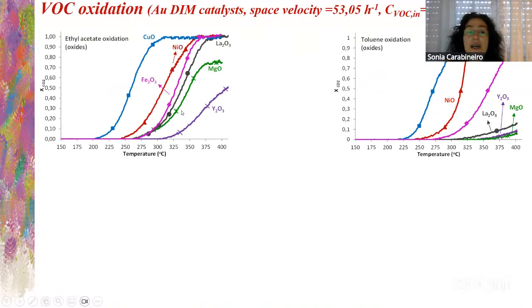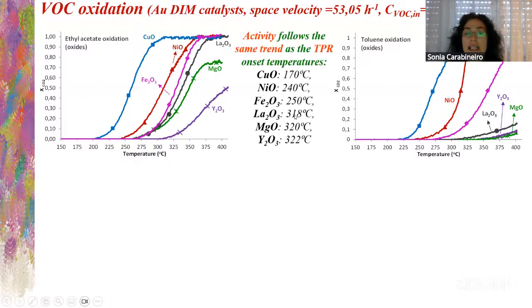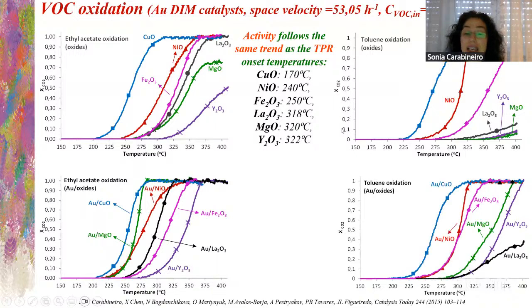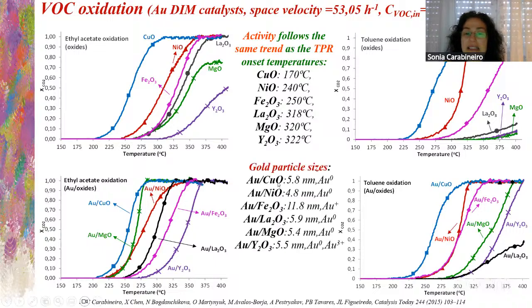Here it's several oxides, okay, several oxides for ethyl acetate and for toluene oxidation, for the oxidation of two different VOCs. And you see that the activity follows the trend of the TPR onset temperature. So it exactly follows the same order. If we add gold, we see that the order changes a little bit, and it has to be somehow related also with the gold nanoparticle sizes, see more or less here. And so we see that both factors are present.